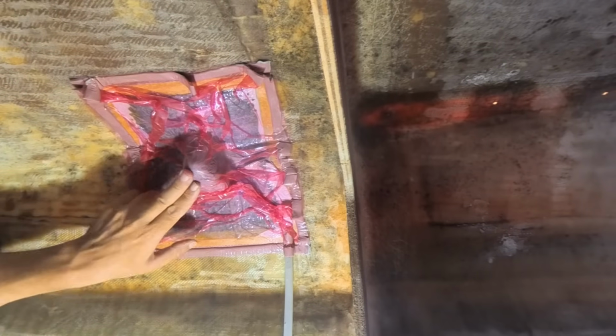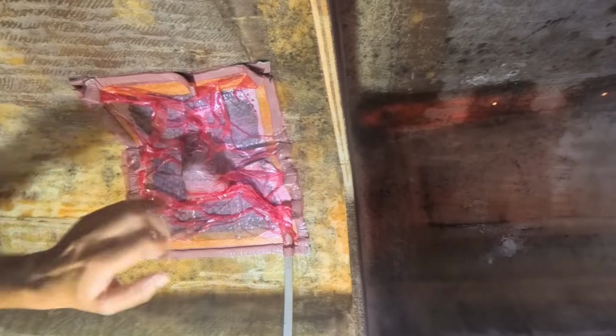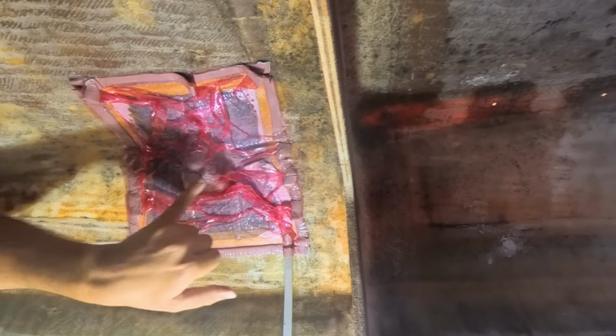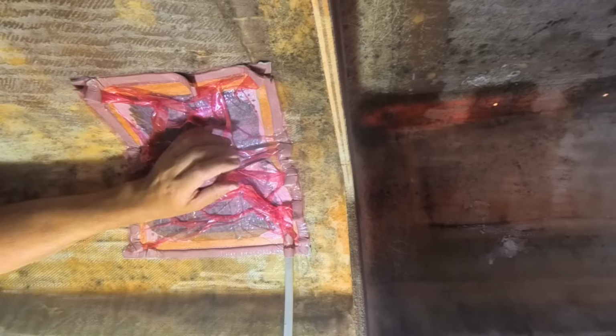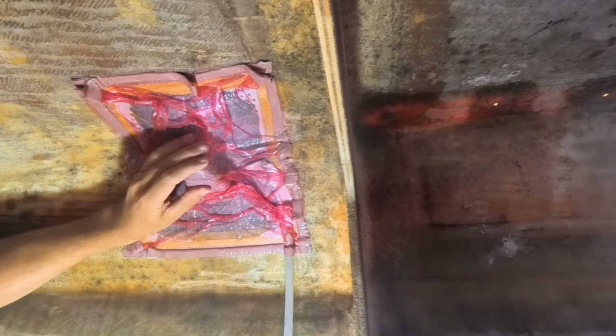But normally you don't want it to be bleeding out this much. You want to see all of these dots. But sometimes, this is a classic case where you have to prioritize one thing over the other. You laminate it wet, get it on there fast, smash it on there, and then you use the fact that you're going to vacuum bag this thing to bring things back to the right thickness and the correct fibre to resin ratio. So you have pretty close to full vacuum.